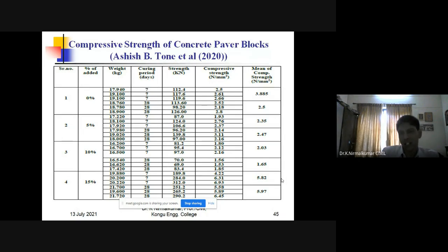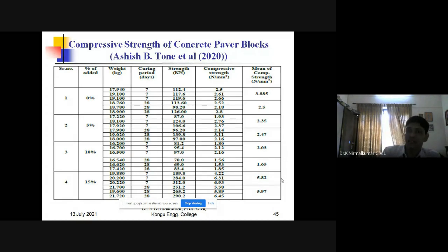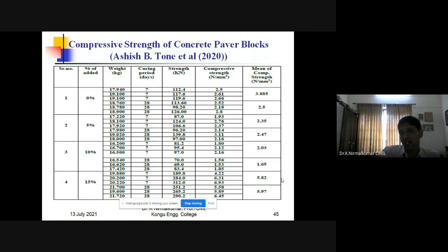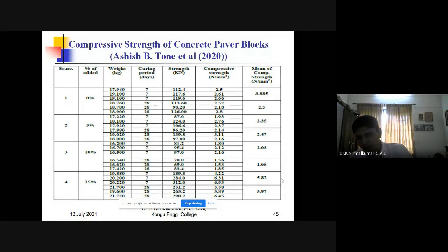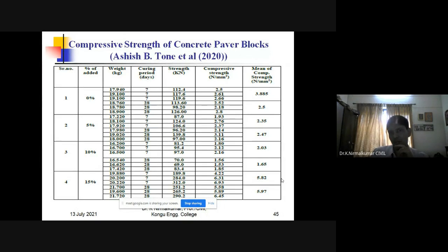He did the same experiment for the paver blocks. For paver blocks, for 0%, for 28 days of curing, it is 2.5 Newton per mm square, and for 5% replacement, it is 2.47 Newton per mm square, and for 10% at the end of 28 days, it is 1.65 Newton per mm square, and at 15% it is 5.97 Newton per mm square.